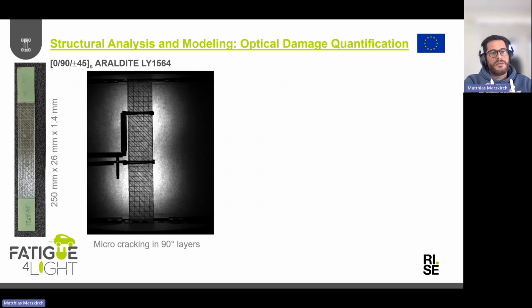Here you actually see a different layup. And what we see here on the specimen is that it has a translucent character. That means you can place a camera in the back of this tensile specimen, and it's shining through that. So machine vision cameras with 8-bit have been used, so that we get gray levels in the range of 0 to 255. And here you actually see the extensometer while we're doing a tensile test.